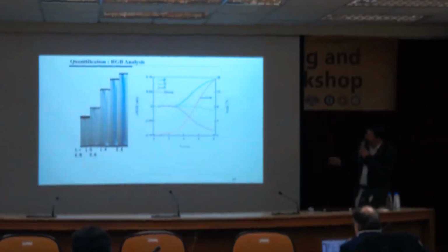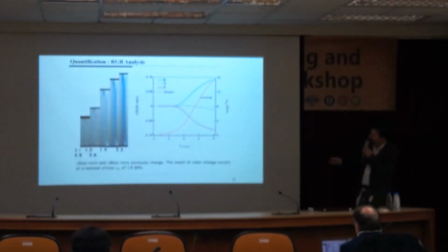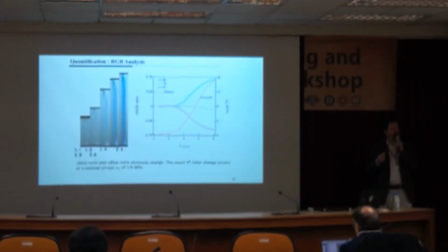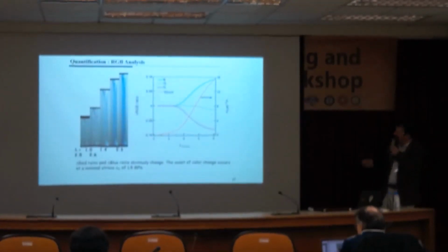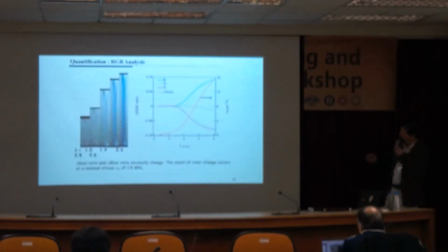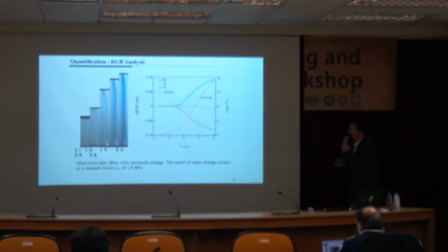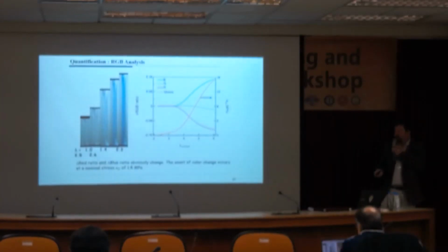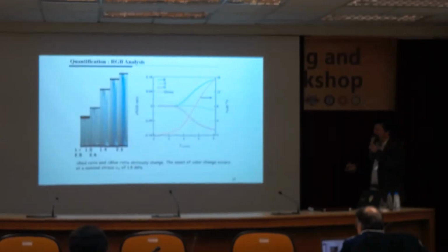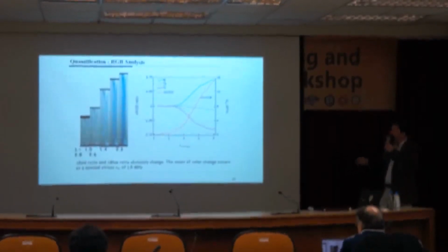So what you get is this. As you stretch your material, you change the absorption. It spatially varies, so if you want to actually use this data quantitatively, there's a bit of averaging to do, and you have to take the ratio of the different colors. Sorry for this. You can see here the blue component, the green, and the red. The interesting thing is that even though this spectrometer would be better to get the total spectrum, this is something you can do with a simple RGB camera. So with a cheap camera, you can get pixel by pixel information about the RGB.